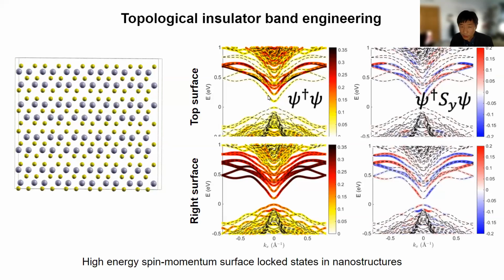In the case of a slab, we should get this linear dispersion, the Dirac cone, as we showed in the previous slide. But because of this quantum confinement, we open a very small gap. And what is interesting is that the surface states no longer reside on the low energy Dirac band, but in fact migrate to the higher energy bands. Whereas on the other surface, they still reside on the Dirac bands.